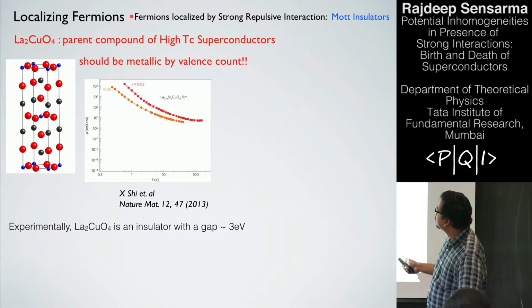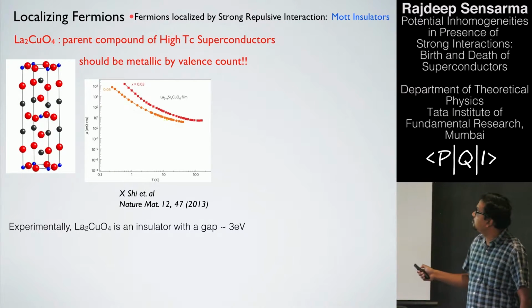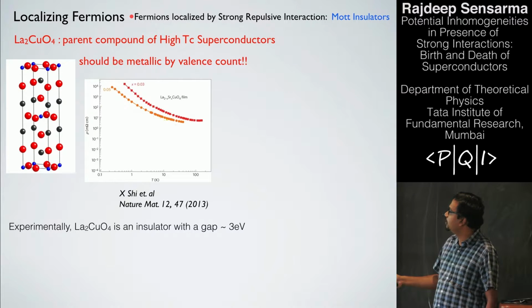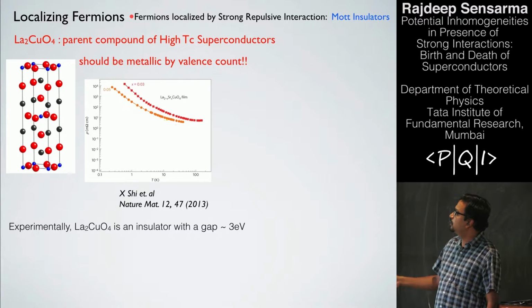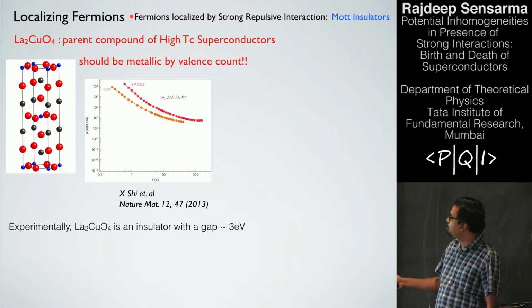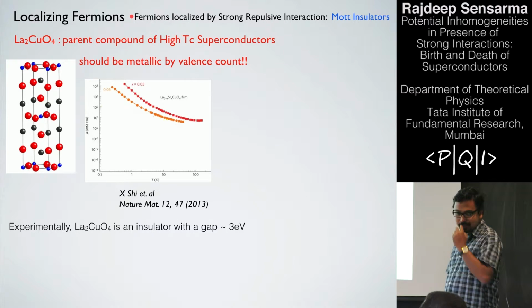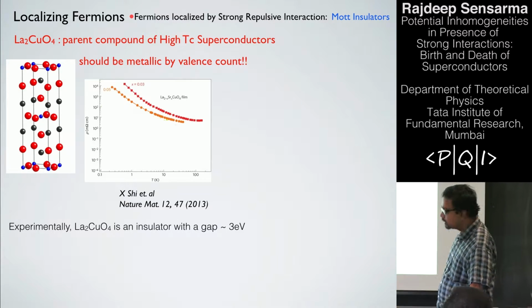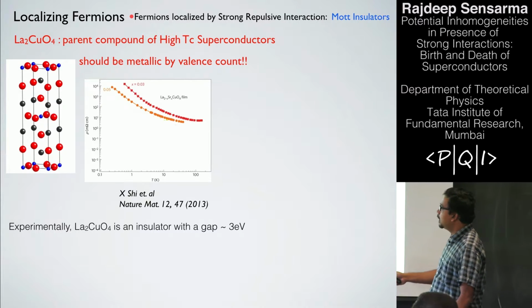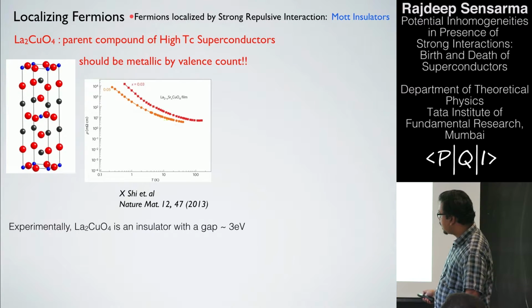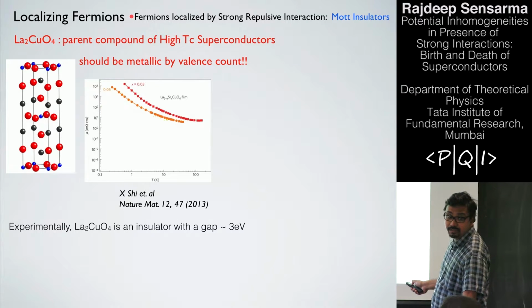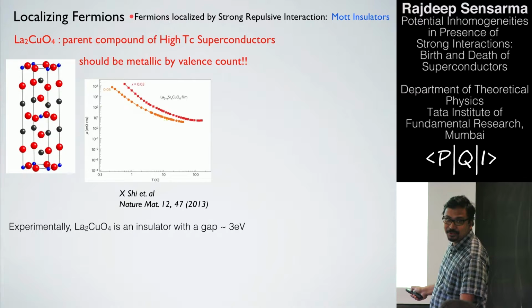The example, as I was telling, is that if you look at parent compounds of high Tc superconductors, and if you just do basic chemistry, it should be metallic by valence count. But if you look at very low doping and look at resistivity data, you see that it shows insulating behavior. This is very close to one particle per site. It is an insulator with a gap of 3 eV, and this is what I was saying, that the spin scale where you have antiferromagnetism is about 150 meV, which is very different from this.